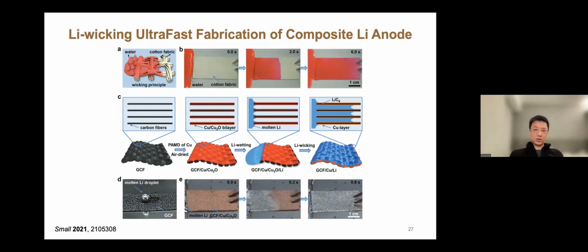to wet a very tiny surface. So what we found is that we can learn from a textile which wicks sweat, and use that analogy to develop metallic textiles as a current collector that can wick molten lithium. Our sweat can be wicked by fabric in less than a second, which allows it to evaporate and dry very quickly. In our case, we also design a current collector with a similar structure, but coated with metals and then cuprous oxide, which has a high affinity with lithium. Then we contact the lithium on one end, and the molten lithium can be wicked into these current collectors extremely rapidly.